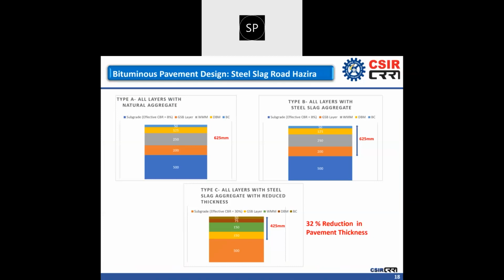We built a conventional road using conventional natural aggregate and bitumen for around 300-meter length. The road is designed for 100 million standard axle repetitions for a 20-year design life. We determined the pavement composition as per the recommendation given in IRC 37, and then constructed a second section using the thickness as prescribed in IRC 37 for a conventional aggregate road, and we built one section of 250-meter length of this particular thickness. Once again, the pavement thickness is around 625 mm in the conventional as well as in the steel slag road section, as suggested in IRC 37.